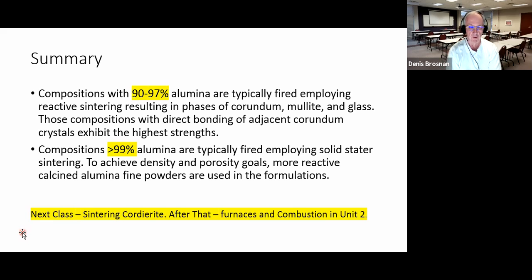Well, I hope that was interesting to you in firing alumina. It's certainly not comprehensive because you could have a whole course on firing alumina. But it's a little bit different firing situation. It's the first case where we've had direct bonding of the majority crystal phase, corundum, aluminum oxide crystals, direct bonding across the matrix to give the physical properties that we wanted. And liquid phase played a minor part or no part in achievement of the fired microstructure, the fired properties.